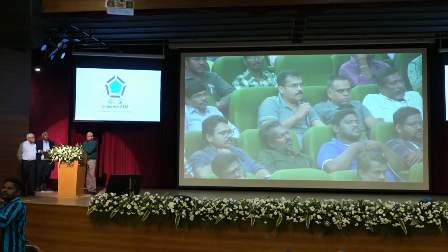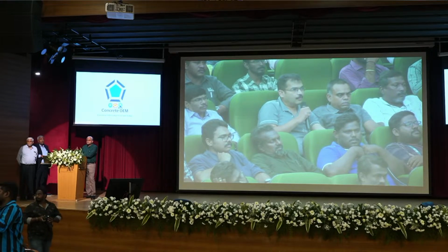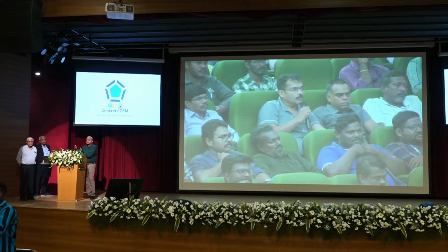Yeah, so service life modeling means you're trying to assess the maintenance-free life of a structure. Typically, when you talk about durability, the primary mechanism of deterioration is corrosion of reinforcing steel. So, to model the service life in a corrosion environment implies that you judge the life of the concrete before corrosion will initiate in the reinforcing steel. So, for example, if you are designing a concrete structure for 100 years, your modeling should clearly show that in a chloride environment, supposing you're in Chennai, the chlorides will not initiate the steel corrosion in that 100-year period. That's what is service life modeling.